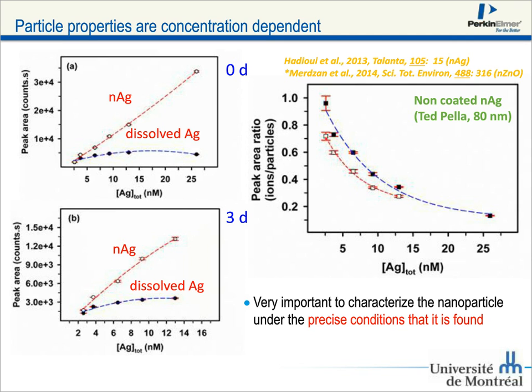as you decrease the concentration, or as you increase the concentration. So what this implies is that we can't just measure our stock solutions and then assume that we're going to have the same answer at any dilution or any concentration. In this case, and this was done with 3 different analytical techniques, several different coatings, several different nanoparticles, we get an increase of dissolution or oxidation in the case of the nanosilver as we go to lower and lower concentrations. So it's vitally important that we're characterizing the nanoparticles under the exact precise conditions where we want to be doing the measurements.